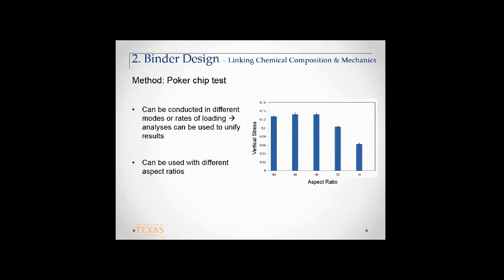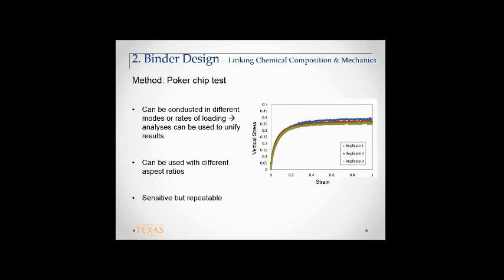We've tried different aspect ratios. If you correctly account for the confining stresses, you'll see that the true vertical stress is almost constant as long as your aspect ratio is 40 or higher. That means your diameter to film thickness ratio is 40 or higher, and you get very consistent results. If you go from 40 to lower aspect ratios, that means you have a thicker film, and you don't get as much confinement. So what you get is not fracture but flow. You transition from fracture to flow. Over here we see crack nucleation, cavitation, and the transition from cavitation to flow-type behavior, and so forth. It's a sensitive test, but it's repeatable.